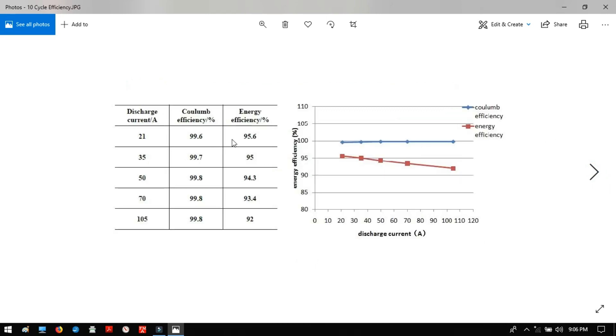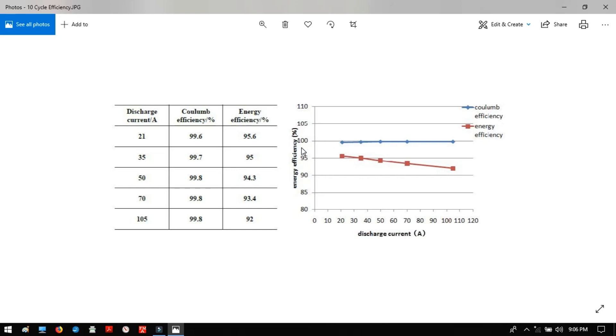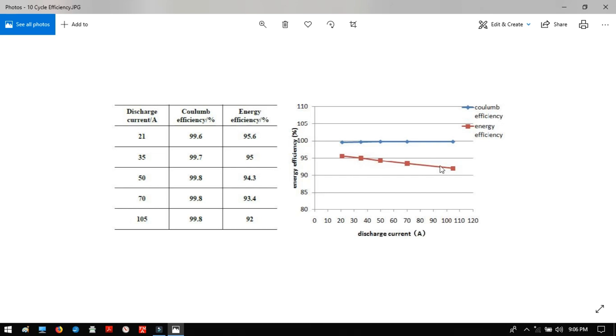And this gets into the difference between amp hour or coulombic efficiency and energy efficiency. Joules, watt hours, calories is energy efficiency. So here we can see that your coulombic efficiency or amp hour efficiency doesn't affect too much. This tiny little difference might be just in measurement error, but it doesn't affect too much as your amps increase. But your energy efficiency of that cell, the round trip, how much you put in charge and how much you put out discharge, your total round trip energy efficiency goes down as your amps go up. Well, where does that energy go? It goes into side reactions. And that's why you have less cycles and less years and so forth. The energy is spent doing other things other than coming out as electricity.